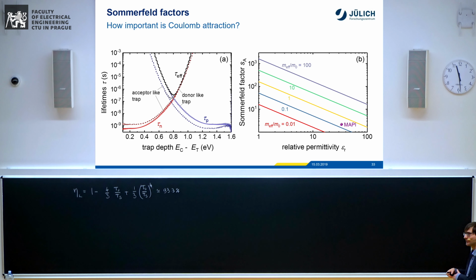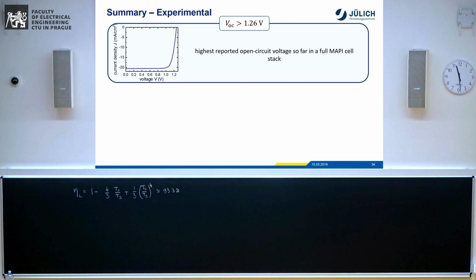So according to theory, Coulomb attraction could also make the transition less likely. That's something I don't understand, I don't understand how this can be. If you want that in theory, you need very low effective masses and very high permittivities, and I don't know what happens then. Maybe there needs to be another theory that makes sure these lines don't go below 1.